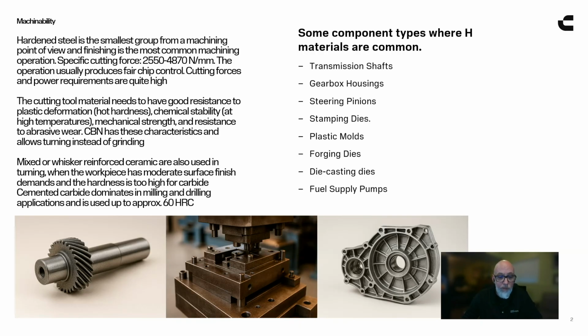It's really important for cutting materials to have a high hardness or a high wear resistance. And the way that we do that is through the composition of the cutting tool material. It's really simple. It's tungsten carbide versus how much cobalt is in that mixture. Basically, the more tungsten carbide there is, the higher the wear resistance is, and the more heat that tool can take without suffering what we call plastic deformation. That's basically when the substrate melts and the tool loses its shape. It's no longer sharp. It didn't break. It didn't chip. It didn't wear out. It just melted and lost its shape. That happens when there's too much cobalt in the mix. So we're looking for high tungsten carbide mixtures.